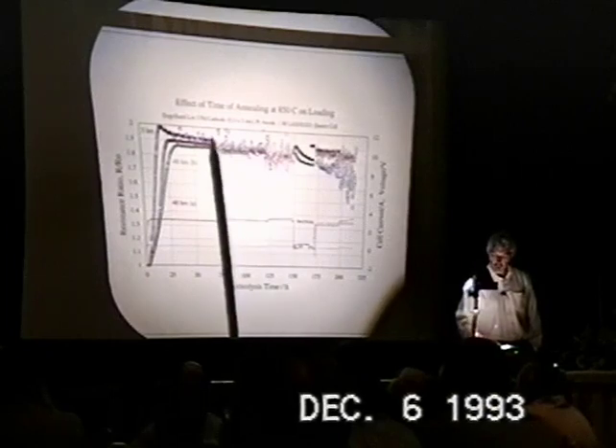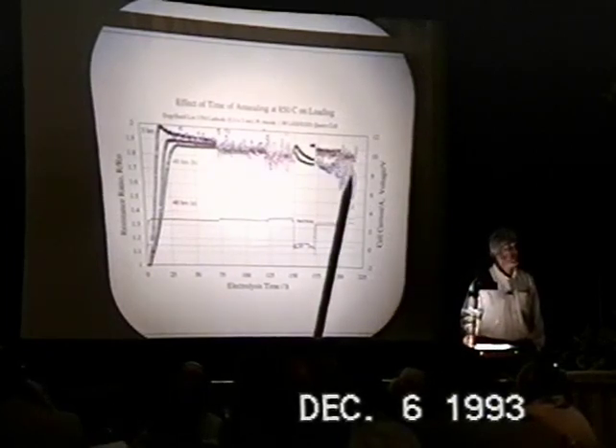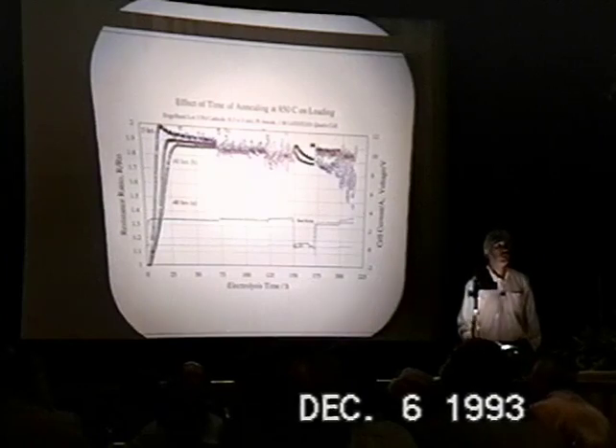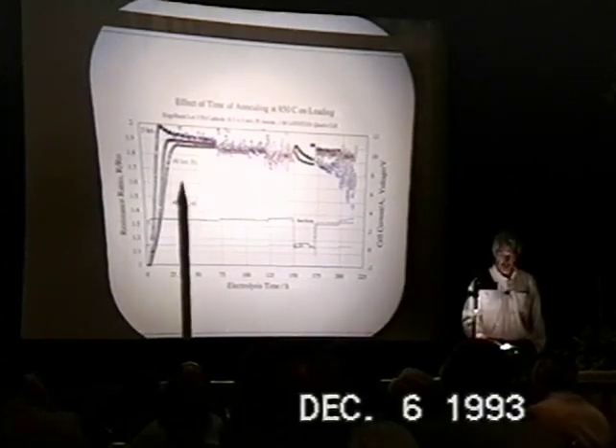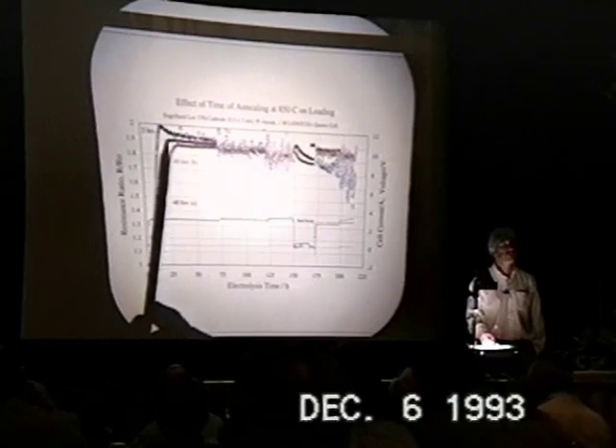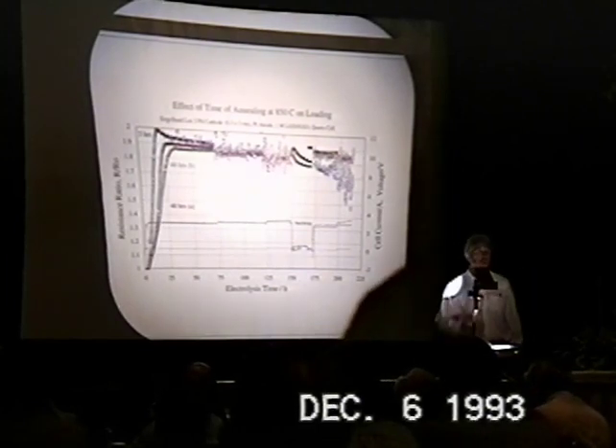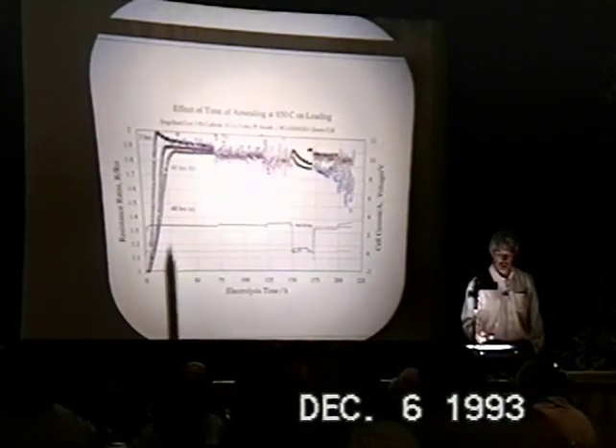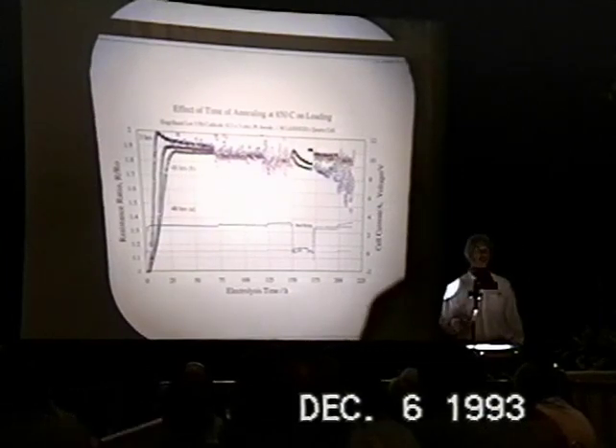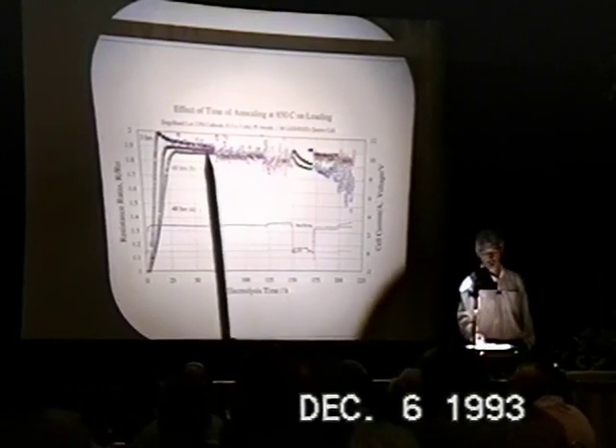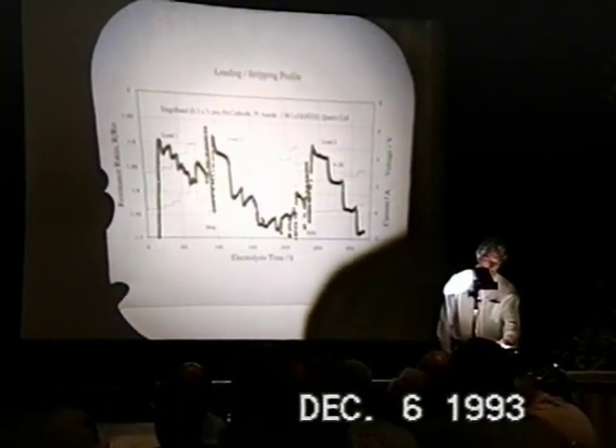But at modest current densities, up to about 80 milliamps per square centimeter, the resistance ratio continues to go down for this purple cell, annealed for 3 hours, whereas the 2 examples annealed for 48 hours. Worse performance, faster loading, it got there faster, hit the maximum, and was relatively unchanged, did not respond to increasing current. My guess is that that annealing procedure, whatever the effective time was, whether it be metallurgical or impurity derived, the increase in contamination or structural change has caused some disbenefit to the loading process.